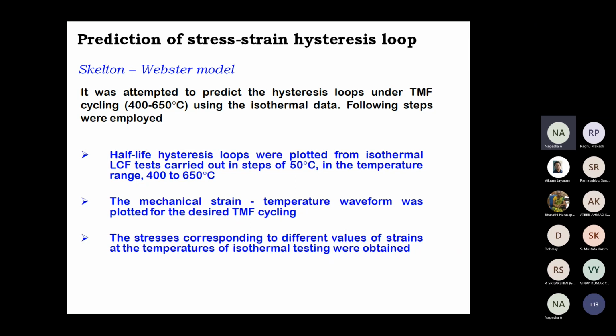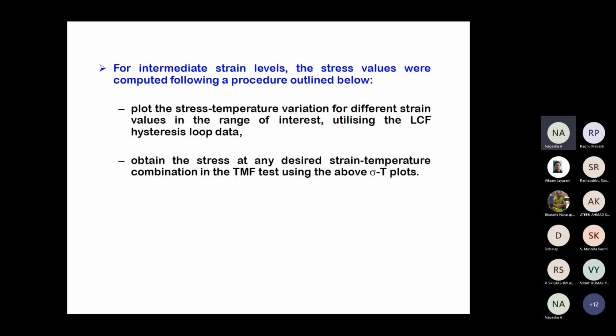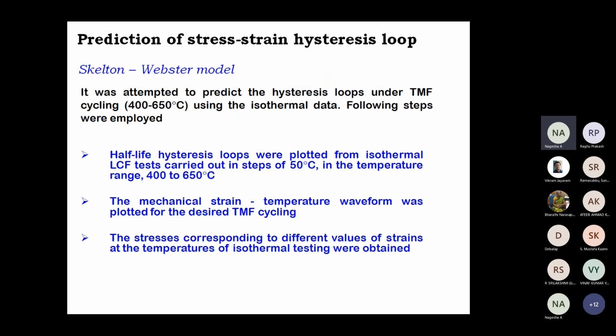We try to predict the hysteresis loops under thermomechanical fatigue using the isothermal database, for which a simple model proposed by Skelton and Webster was employed. We carried out a set of isothermal tests at various temperatures in steps of 50 degrees, from 400 to 650 degrees. The mechanical strain versus temperature waveform was plotted for the desired TMF loading, and stresses corresponding to different strain values at the different temperatures of isothermal testing were obtained, and this gives only a few points.